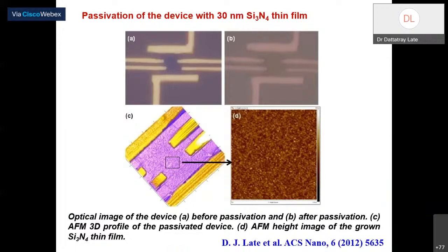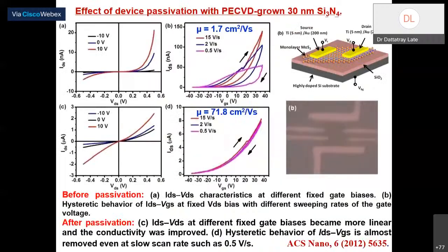I have coated the device with silicon nitride. Okay, silicon nitride coating has to be done at high temperature and in vacuum condition. So it is expected that at high temperature, more than 300 degrees Celsius, all water molecules have been removed, and very little remains because this is in a vacuum condition. So a lot of oxygen functionality has also been removed. Once you take the device off after coating, we found that the device is giving very nice performance.